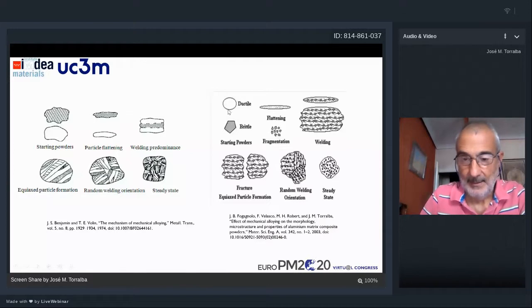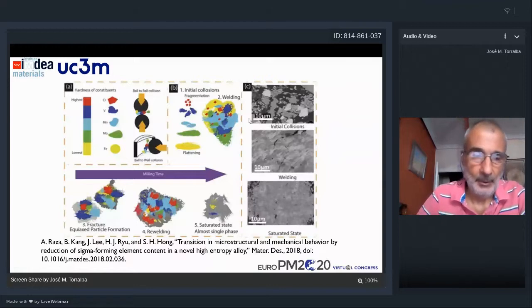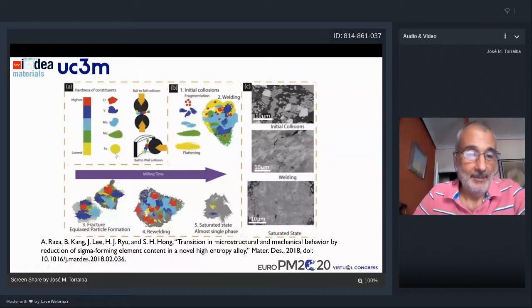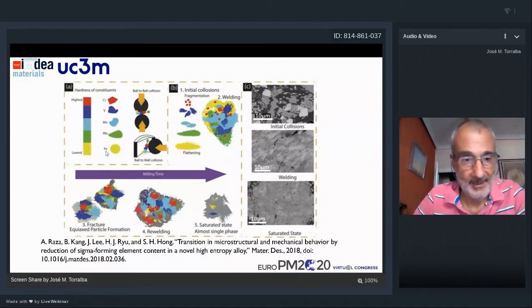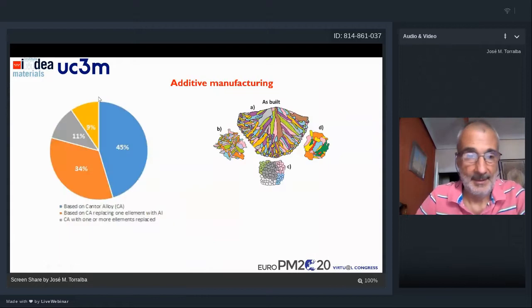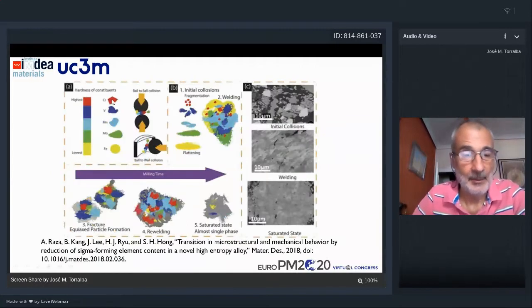In high entropy alloys, there is a very interesting paper published by Raza and collaborators, in which they demonstrate that the mechanism that is followed is the ductile-brittle, not the ductile, because when we mix 5 elements, like in that case chromium, vanadium, manganese, moly, or iron, some of those metals are really hard metals, and there are others like iron or moly with a much lower hardness. So that means inside the mill, you can have powders with a much higher hardness than others. So those hard particles act as a ceramic, as a brittle particle in the development of the final particle. So we can consider here the steps similar to the brittle-ductile mechanism.